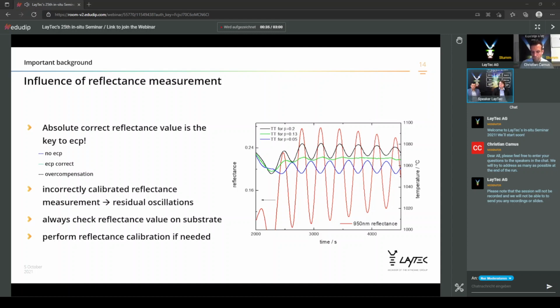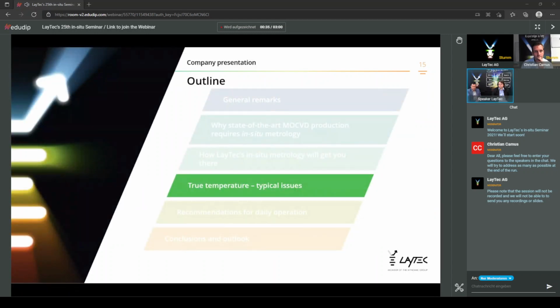So we recommend that you always check the reflectance value on the substrate. For example, for sapphire, the reflectance value you read on the substrate will be 7.5%. If you read other values, you need to perform the reflectance calibration. Well, now Heiko will report typical issues we received from the field, or what we see in many cases in the field, what might happen.